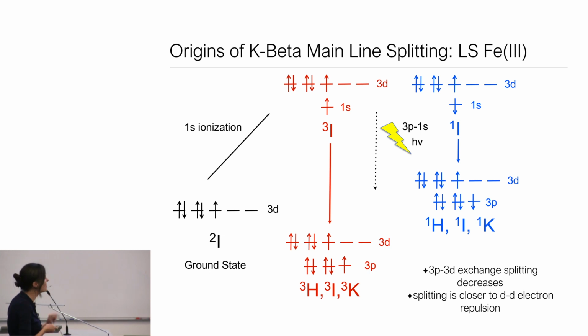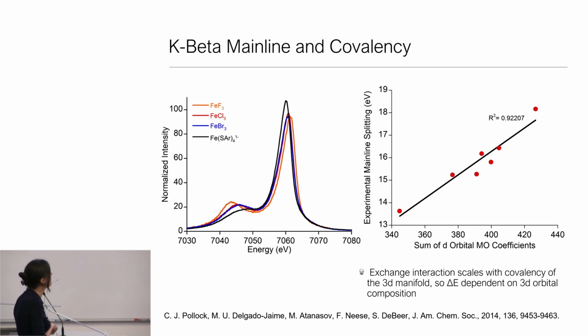But anyway, he actually helped us work through all of this and to understand how these K-beta mainlines can change as a function of ligand identity. What Chris Pollock together with Mikhail were able to show is that we can have high spin iron 3, and these main lines become sensitive to how covalent the complex is, where the splitting decreases because D character is becoming delocalized onto the ligand. And so these actually are measures even of covalency.